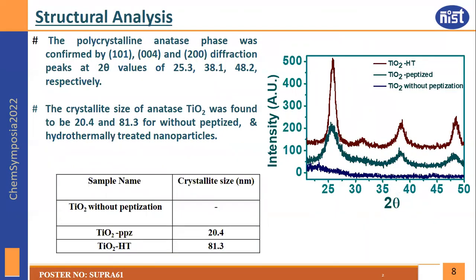The structural analysis of the developed particles was done by X-ray diffraction study, which shows the well-known diffraction peaks at 25.3, 38.1, and 48.2, corresponding to the 101, 004, and 200 Miller planes. The hydrothermally treated TiO2 shows significantly enhanced crystallization of nanoparticles. The table shows the crystallite size of the obtained particles after peptization and hydrothermal treatment.